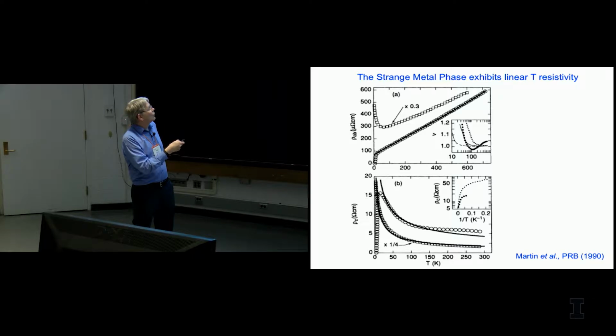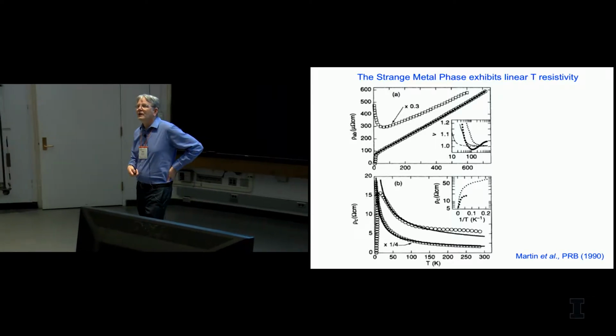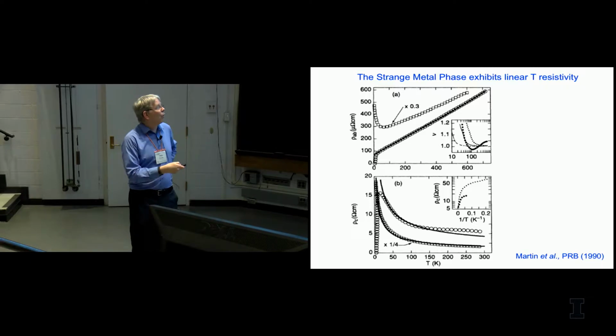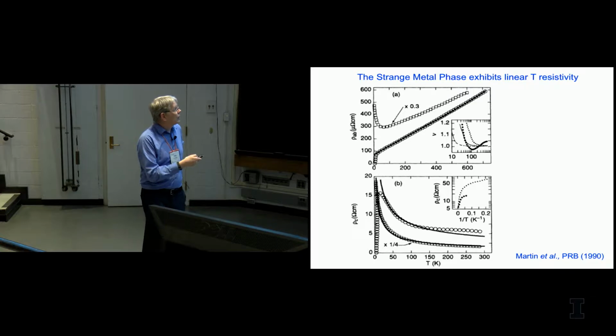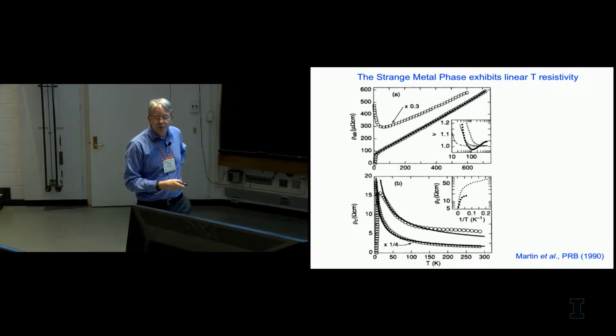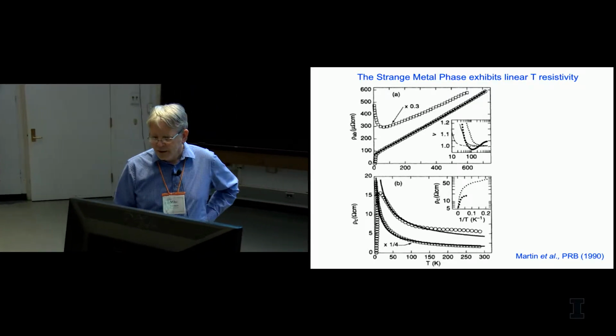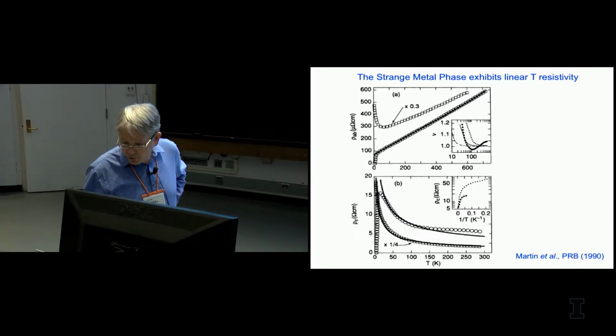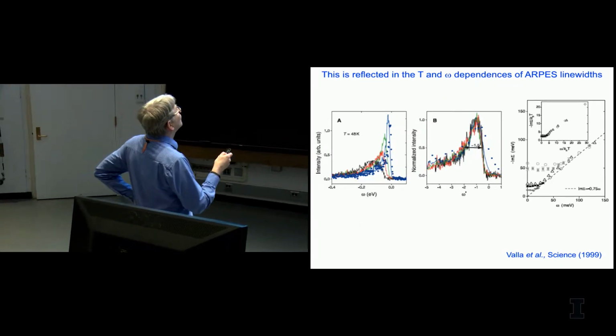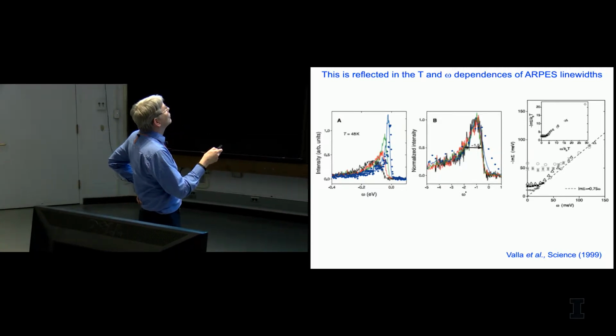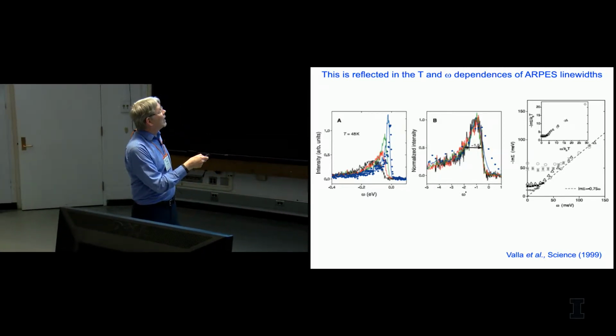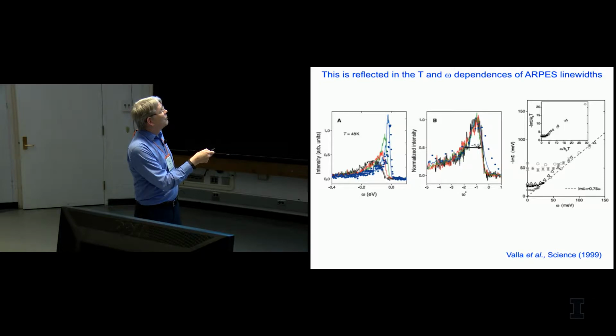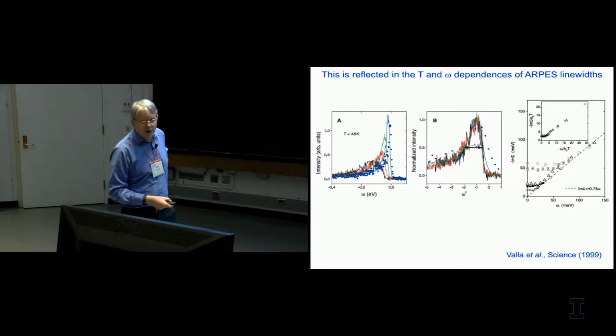The other unusual thing, of course, if you look at the C-axis resistance, is that it is insulating. The material looks like it's going to be an in-plane metal and a C-axis insulator, and then at low temperatures you become superconducting and you establish coherence. And this linear T behavior is reflected in photoemission. So if you look at the omega and temperature dependence of the photoemission line width, this is exactly what you expect. The line width is linear in omega, and then when you get down to frequencies below temperature, it saturates. So you see this saturation effect.